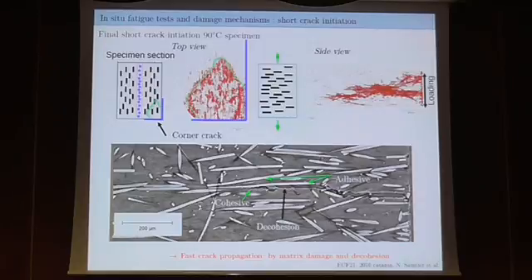This was for the 90° specimen. You can see here, if you look from the top of the specimen, you see the crack from the top. You can clearly see that here you have the fiber direction. The crack is propagating more easily in the direction of the fibers than orthogonally to that one. And the crack is not initiating in the 0° layer, but in the 90° layer. And you can see here that the main mechanism acting here is decohesion between the matrix and the fiber, adhesive or cohesive failure. So this is the main mechanism at 90°.